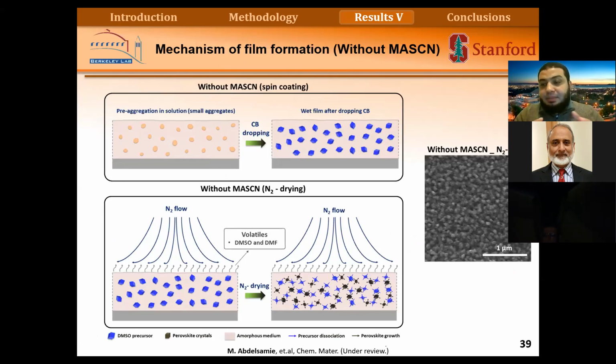And here I'm summarizing the mechanism. So what we have found is, if we don't use additives, we get very small aggregates in solution, and this leads to high nucleation density of a metastable phase, which is the blue material here. It's a complex between the perovskite material and the solvent. So this one is unwanted, and the material is trapped in this. If we do nitrogen drying, this material is relatively stable at room temperature, so it doesn't decompose. So we get very small domains of the perovskite crystals, which is marked here as black, and we have a lot of material that is left as the blue material, which is the intermediate complex that we need to remove. And we cannot remove this at room temperature. We have to heat the film and anneal it in order to get rid of the intermediate phase.